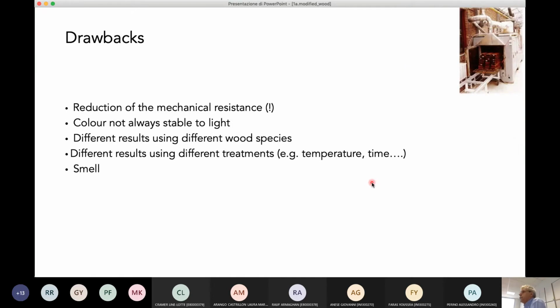There are some important drawbacks to remember. The first is the most important. The mechanical resistance of this material is strongly reduced. So, thermally treated wood is good for many reasons, but the mechanical resistance is also considerably reduced, and this can be a problem, especially for building elements. Color is dark, but not always stable to light. We have already mentioned that we get different results using different wood species, and also different results from different treatments. So if you want to buy thermally treated pine, it's okay, but the properties depend on which treatment is the subject.